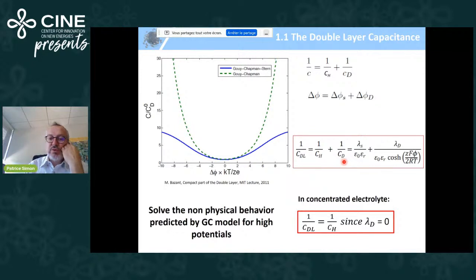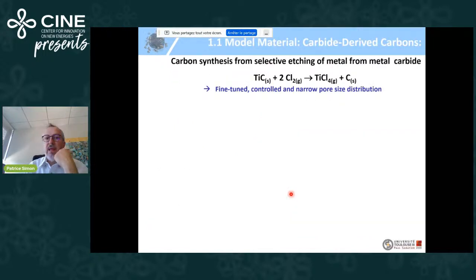However, if you use concentrated electrolytes like we do in energy storage devices, obviously lambda D, the Debye length, tends to zero because there is no diffuse layer if the electrolyte is super concentrated. So finally, your double layer capacitance is more or less the Helmholtz capacitance. And this is what we will consider in the next slides. So to study the ion adsorption in porous carbons, you need porous carbons.